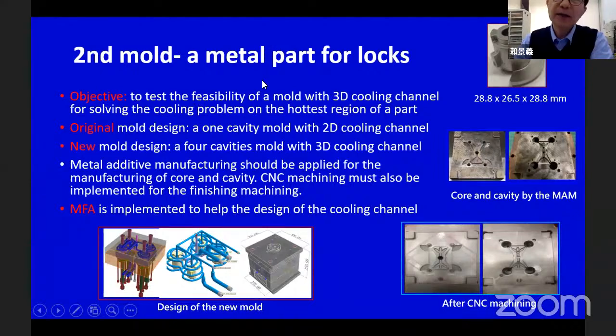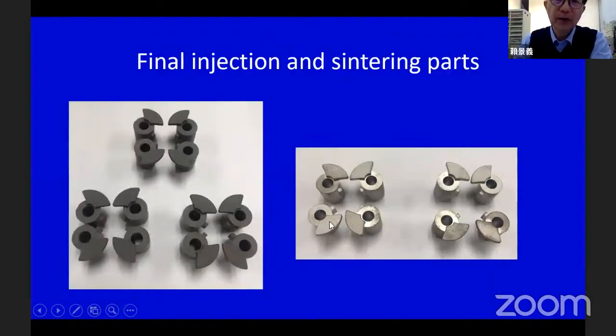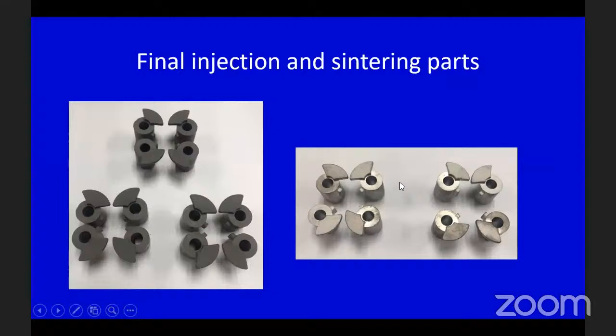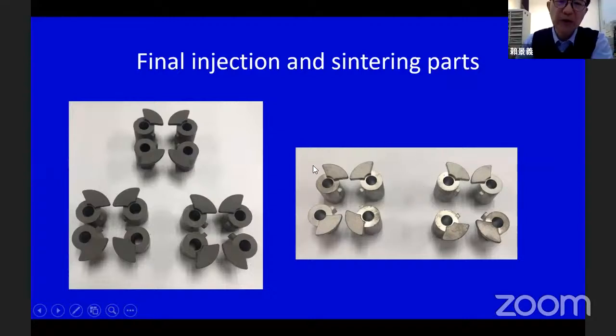And the second one was made 2 years ago. This is the new part and the new mold we came out with. At that time we wanted to check whether the result is acceptable or not. So for the second one, not only did we obtain the green part, we also went on to sintering. So this is the final result we obtained. We removed the wax, and this is the final part, and the final part seems acceptable.